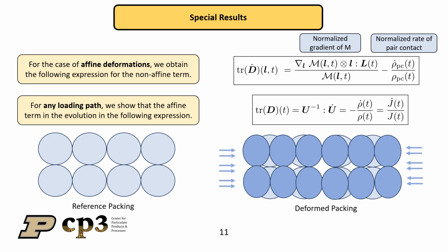For the case of affine deformations, we find a specific expression for the non-affine term in our evolution equation that relates the normalized gradient of m to the evolution of pair contacts. We also furthermore see that for any loading path the affine term reduces to the rate of relative density, or the rate of the Jacobian, which is illustrated below.